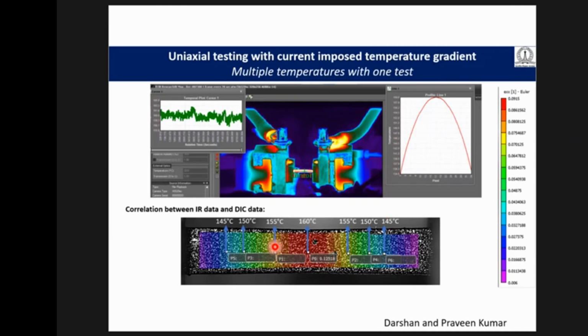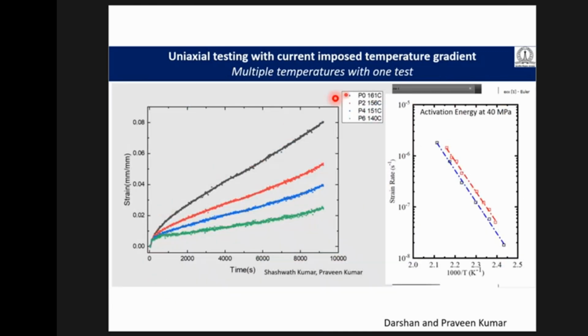So I've got it the other way around. The current is passed through the sample. The grips are not heated, and so the cooling is from the grips. So the region near the grips is actually slightly colder than the region in the middle. So this is 160, and the ends are at 145. And so again, it's a creep measurement. So you can now measure creep at different temperatures. You can plot activation energies. And one of these curves is from a single experiment with multiple temperatures, and the other one is from individual tests done at half a dozen different temperatures.